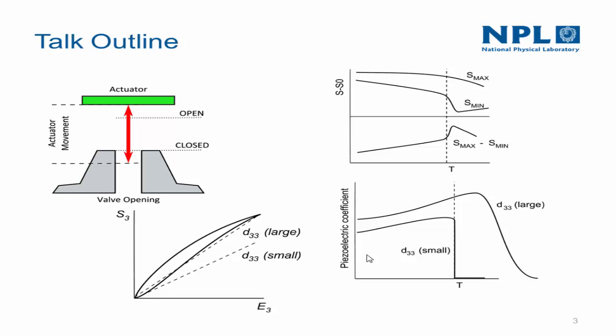So this top graph here shows, for instance, this line here is the strain, the S min is the strain at zero electric field. And you can see the thermal expansion in that, and we can see clearly the change in remnant strain at the Curie temperature. If we apply finite electric fields or large electric fields, then you go straight through that point and you don't even see it. It's more or less continuous. You wouldn't know that there was a transition there. And so the influence of the Curie temperature on the performance of an actuator is something that you may not see from small field measurements.